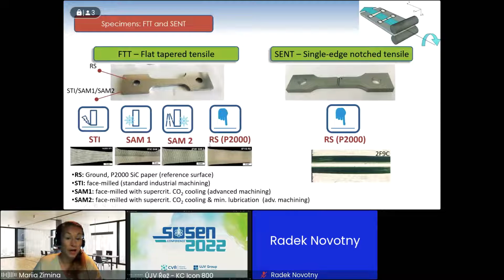First one is RS, which is a reference surface, which was just ground using silicon grit paper, and the other 3 were actually machining. STI stands for the standard industrial machining, which was chosen to compare the results to the actual industrial conditions. The second one was the SAM, which stands for Surface Advanced Machining 1 and 2. And the difference between 1 and 2 is that first one was face milled with supercritical CO2 cooling, and the second one was the same but using the lubrication.